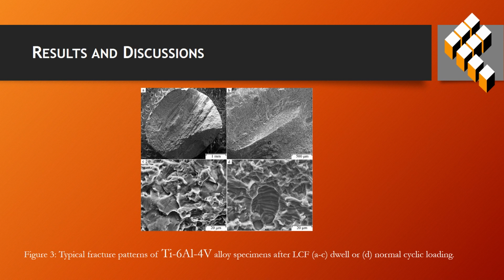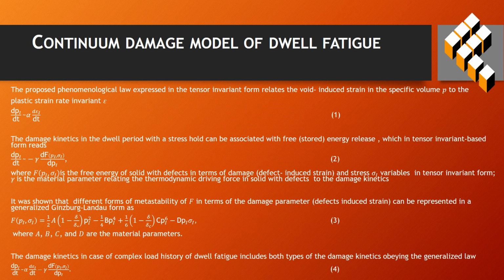3. The developed concept of modeling of titanium alloys based on the duality of damage kinetics in dwell fatigue loading regime allowed us to elaborate the strategy of structural study, which is expected to substantiate the relationship between the structural parameters of alpha, beta phases and the phenomenological parameters that govern different mechanisms of damage accumulation in the low cycle fatigue and stress hold regime.